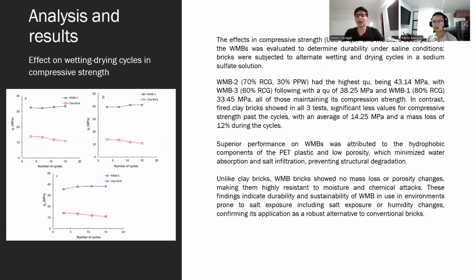WMB2 has the highest QU, that is compressive strength, being 43 MPa. WMB3 has a following QU of 38 MPa, and WMB1 33 MPa, all of those maintaining their compression strength. In contrast to fire clay bricks, which show in all three tests significantly lower values for compressive strength past the cycles, with an average of 14 MPa and a mass loss of 12% during the cycle.